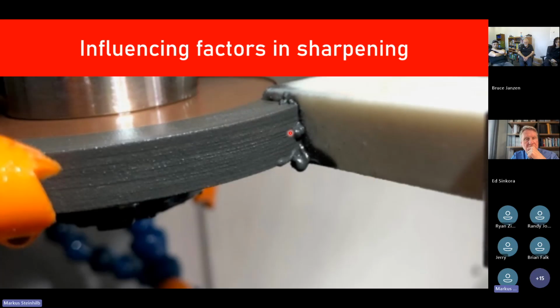In this slurry is diamond powder, rests of the sharpening stone, and rests of the bonding system. So I take it otherwise you would just be pushing the diamond back into the wheel, is what you're saying. Yes, that's right. And you also push the corundum into the pores of the bond system, so you glaze it a little bit and smooth the surface of the grinding wheel. With the soaked sharpening stick, you have a more sharpened, more open porosity of the bonding surface. Right. Okay. It's to reset the bonding system.